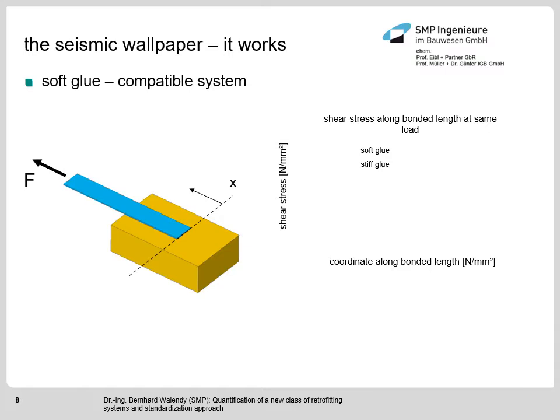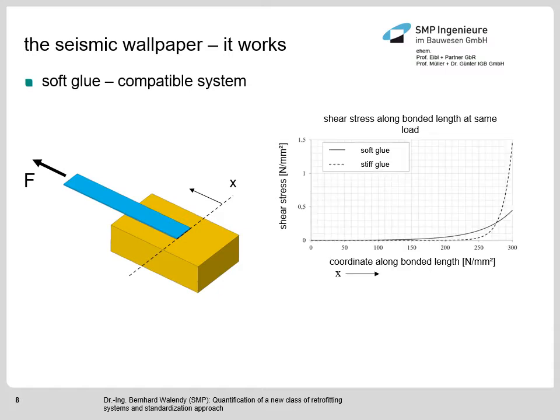Now let's analyze the distributed shear stress along a fiber reinforced polymer under an applied load which is indicated with F. We have a look at two configurations, one soft glue configuration and a stiff glue configuration. For the same load, you can see here the maximum shear stress peaks can be significantly reduced by the use of a soft glue. It's like the weakest link within the mechanical system, due to the brittle cohesive failure mode, could be fixed, let's put it like this, by the use of a soft glue.